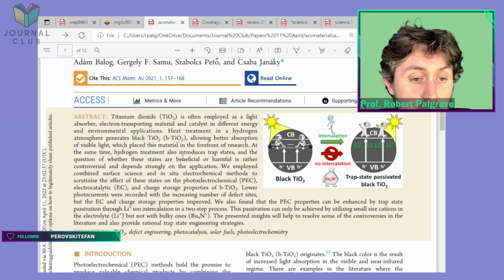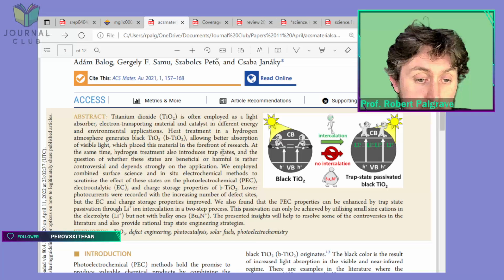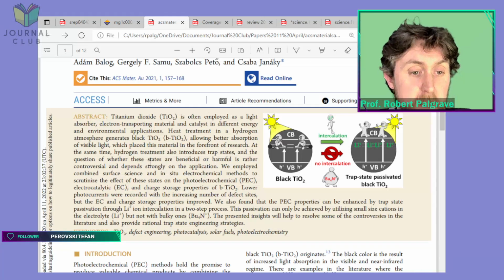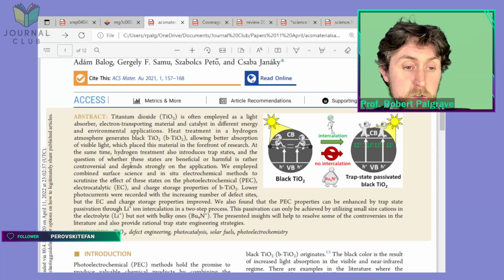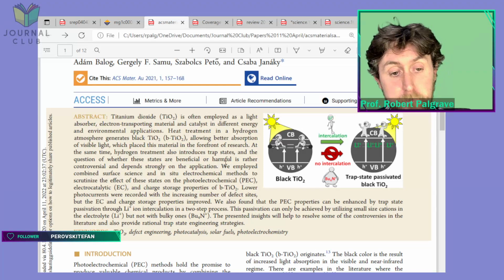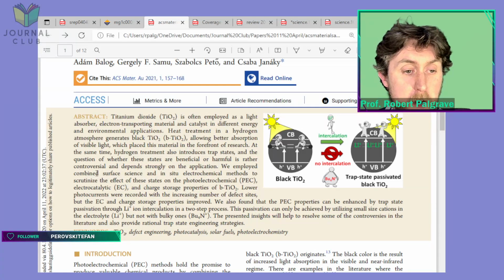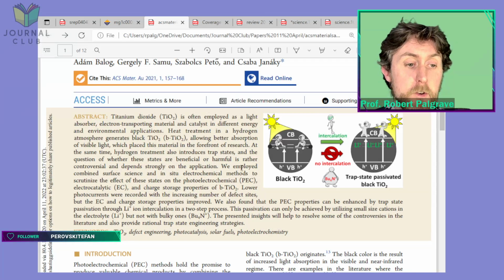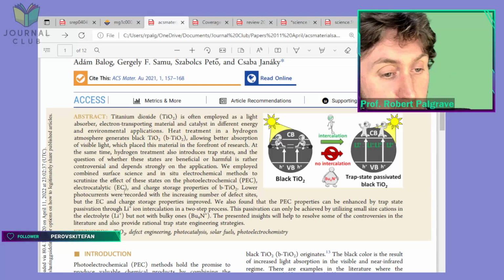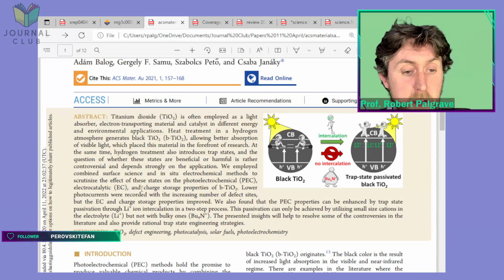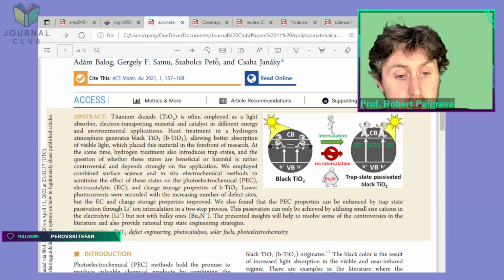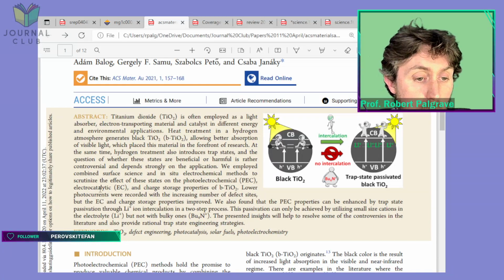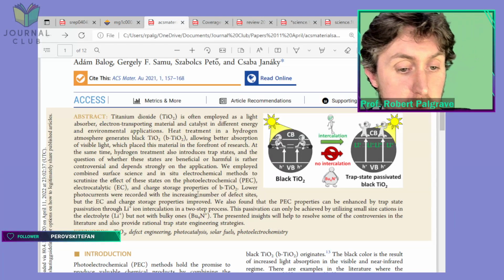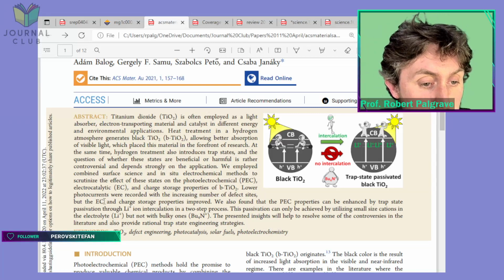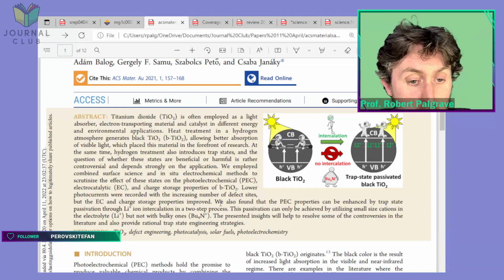At the same time, hydrogen treatment also introduces trap states. We'll discuss that later on. And the question of whether these states are beneficial or harmful is rather controversial and depends strongly on the application. Fair enough. We employ combined surface science and in situ electrochemical methods to scrutinise the effect of these states on the photoelectrochemical (PEC), electrocatalytic (EC) and charge storage properties of black TiO2. Lower photocurrents were recorded with increasing number of defect sites, but the electrocatalytic and charge storage properties improved.